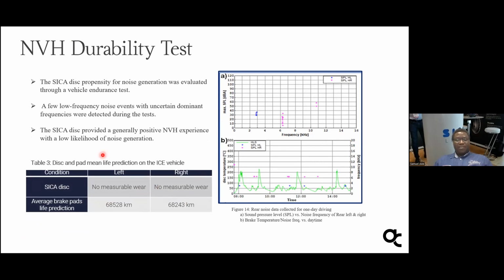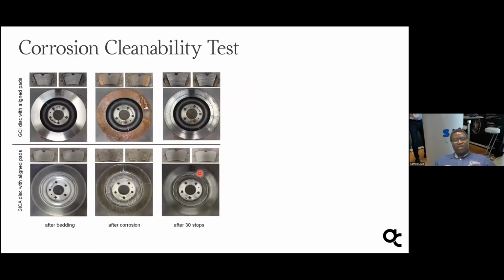And based on this test result, we evaluated the lifespan of the pad and the disc. Take note that the vehicle that was used is an ICE vehicle, not an electric vehicle. Based on this result, we see that for the SICA disc, left and right, there is no measurable wear, which confirms the excellent wear resistance of the disc. But for the pad, we evaluated the lifespan to be around 68,528 kilometers for the left part, while the right was evaluated at 68,243 kilometers lifespan. And we also look at the corrosion cleanability of the disc. From here, we compare the traditional GCI brake disc and the SICA disc.